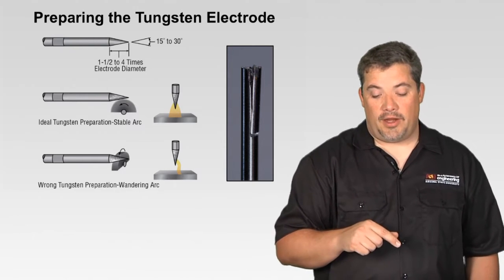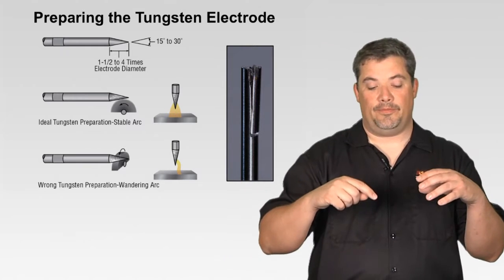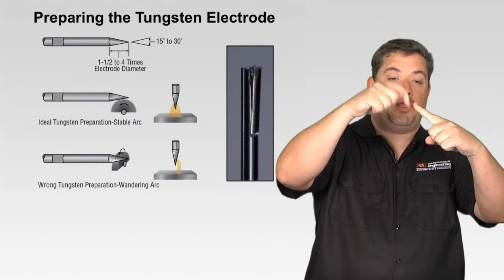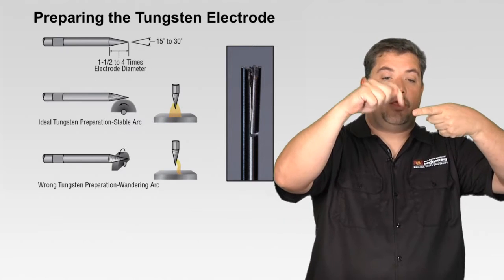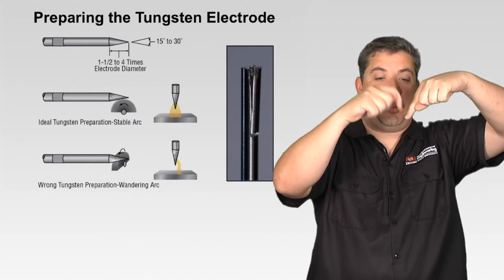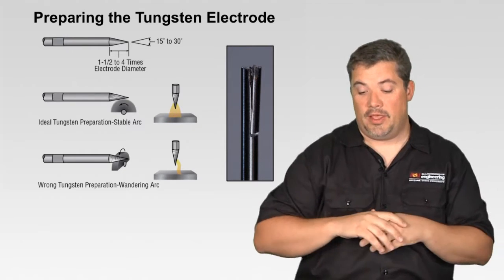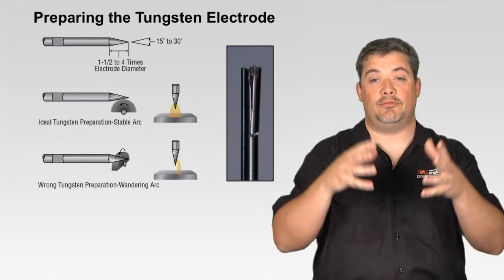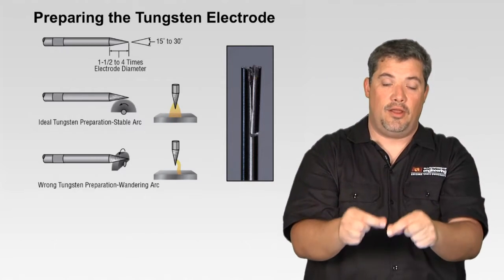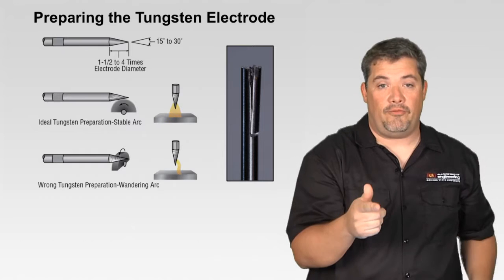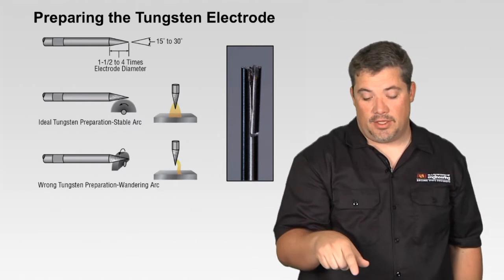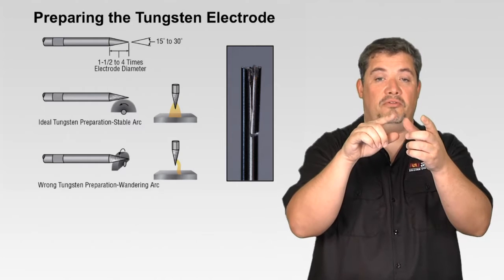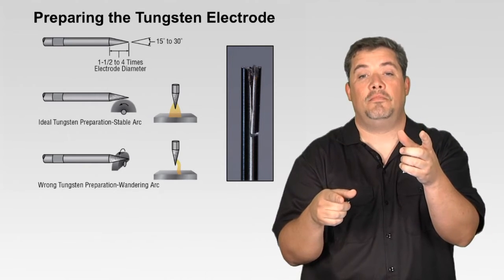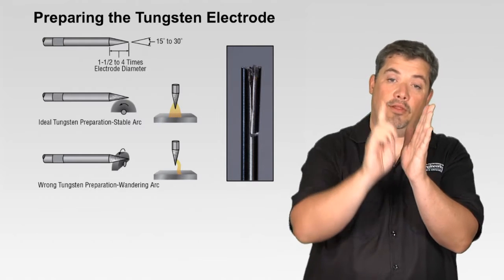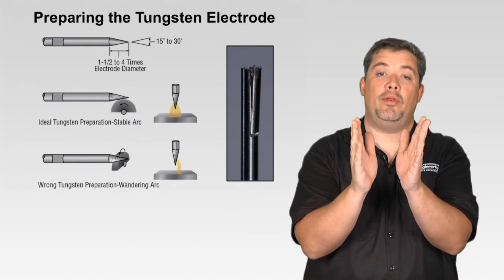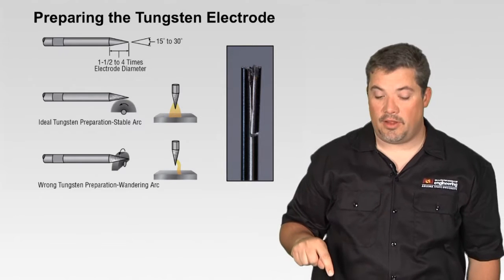It's very important that you grind it in the right direction. So if you're grinding your tungsten and the wheel is spinning this way on my tungsten, that's what I want it to do. I don't want to go sideways, and I don't want my tungsten to be aiming downwards. And the reason for all of that is electrons take the path of least resistance. So we want to get those electrons to come down off the end of that tungsten right where we want them to go. Because if I sharpen that tungsten in an incorrect direction, you can see it just might say, oh, there's a groove here that I'm just going to pop out that arc off of the side. So the smoother I grind it, the lengthwise that I grind it, the better off I'm going to be able to control where those electrons are coming off of that tungsten electrode.